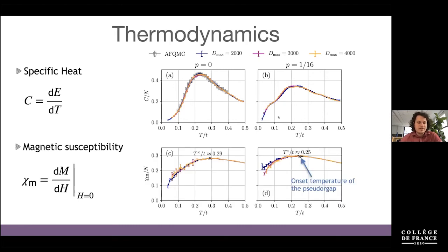Now we can also look at the magnetic susceptibility, defined like this, and it looks like this. Here on the left-hand side is half filling, on the right-hand side is the hole-doped case. What we find is that the magnetic susceptibility develops a maximum at a certain temperature, both in the half-filled case and the hole-doped case. Such a maximum in the magnetic susceptibility is often taken experimentally as the onset temperature of the pseudogap regime.